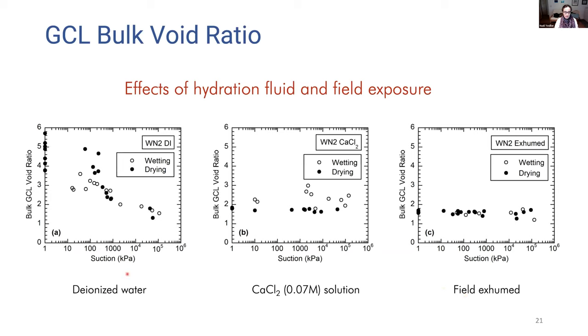For the deionized water case, we see that there is a significant difference in the bulk GCL void ratio as a function of suction. We have a highly hydrated material, highly swollen material, void ratios getting up to the level of 6 or so under saturated conditions, and decreasing void ratios with increasing suction in the system.